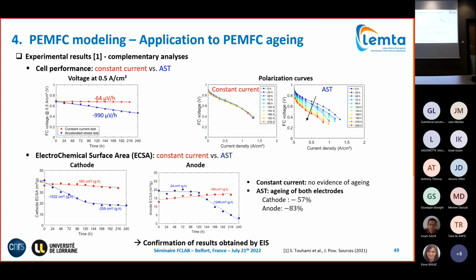So here we see what we observed for the performance measurements, meaning we followed the potential we measured on operation at 0.5 amps per square centimeter. Again, blue is the AST, red is constant current operation. We see almost no evolution of the voltage at constant current, whereas there is a decrease of the voltage during the AST. And as well, here you see our polarization versus time, constant current almost no evolution, whereas for the AST it degraded. Logic confirms EIS analysis.